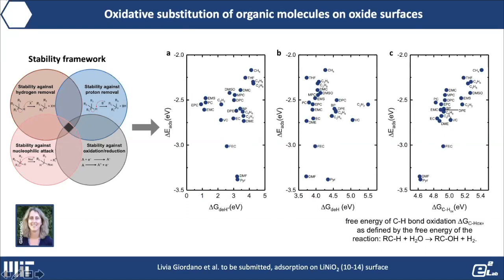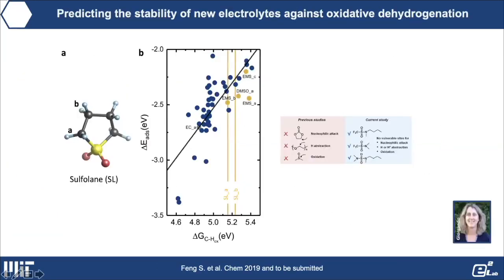Looking at adsorption energy of various molecules on a lithium nickelate surface plotted as a function of dehydrogenation energy, there is absolutely no trend. However, adsorption energy does scale with CH bond oxidation energy — a clear correlation exists. The stronger the molecule is adsorbed and oxidized on the oxide surface, the higher the free energy of oxidizing the CH bond. Using this thinking, new molecules can be designed with reduced driving force for surface adsorption, projected onto this diagram.